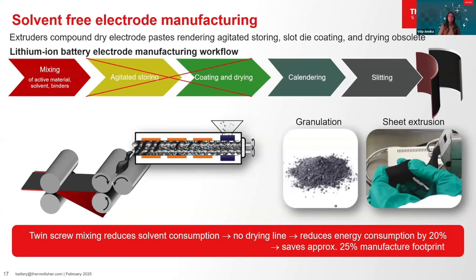The conventional manufacturing of lithium-ion battery electrodes involves mixing active materials and additives with a solvent to create slurry, coating it onto a current collector foil, drying, calendering it to the desired density and height, and laser slitting the electrodes. Twin screw mixers offer the potential to mix electrode materials with binders and additives using little or no solvent due to higher shear energy input. The mixed material can be directly fed into a roller press and calendared onto the current collector foil without drying. This saves a lot of energy.